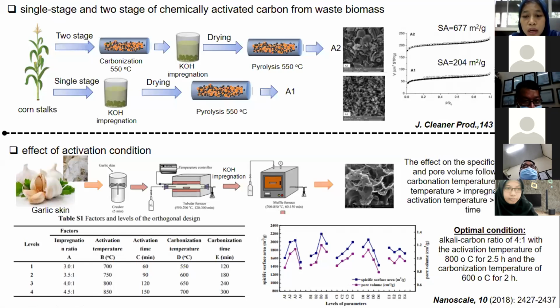For the activation time, we can see that the specific surface area and the pore volume almost linearly increase with the activation time, which may be attributed to the increased pore volume from the activated carbon atoms and the activator in the longer reaction time. For the effect of carbonization temperature, the specific surface area increased with carbonization temperature and reached the maximum value, after which it starts to decrease. And the last is the effect of carbonization time. The specific surface area and the pore volume fluctuated in a small range, indicating the least effect of carbonization time.